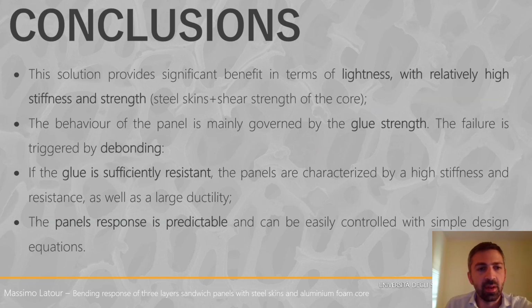In conclusion, the work has shown that the solution is very beneficial in terms of lightness and provides high stiffness and strength. The behavior of the panel is typically mainly governed by the glue strength. The failure is typically triggered by the debonding. Additionally, if the glue has sufficient resistance, the panels are characterized by high stiffness and resistance and high ductility. The panel response can be easily predicted and controlled with simple design equations.